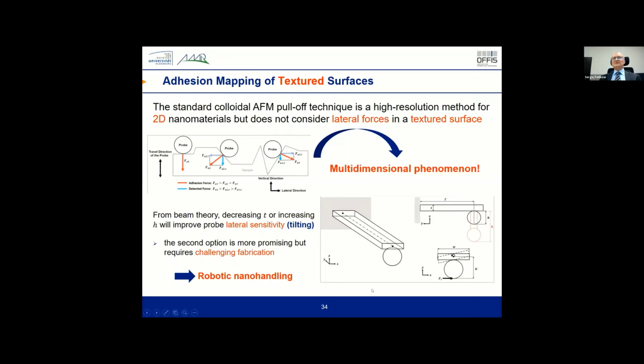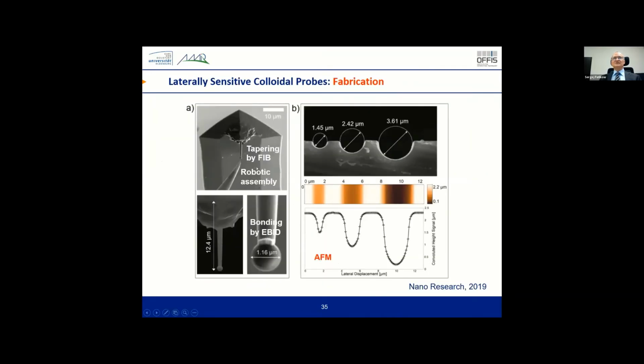And we used robotic handling to introduce new technology for manufacturing this kind of probes at nanoscale, combining focus ion beam for tapering. So we just use a standard AFM tip and remove the material by focus ion beam. So we fabricate a so-called adhesion pocket for the probe, and then we do robotic assembly of this probe. In this particular project, it's just close to 1 micro, to be able to work at nanosurface.